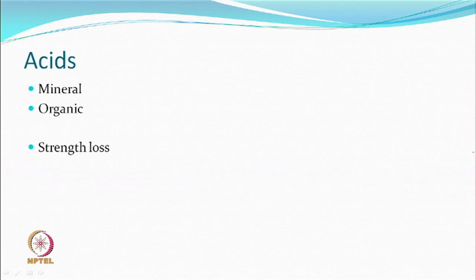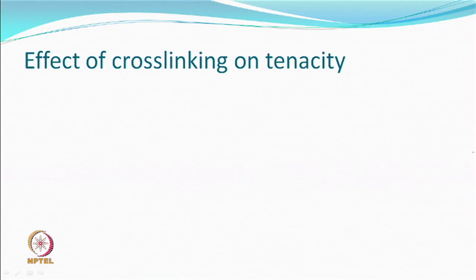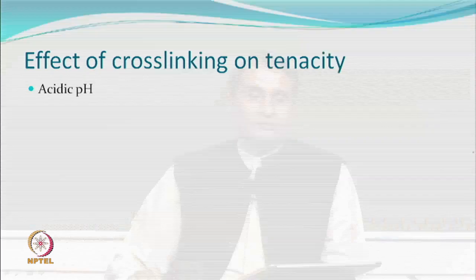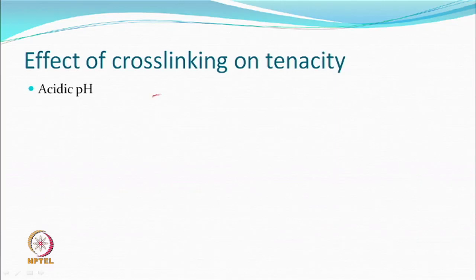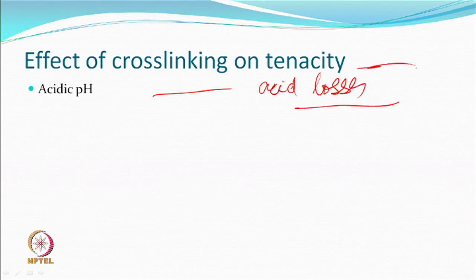And so people would like to not use the acids directly for catalysis, but use something else as catalyst, because of strength loss. I'm sure you know the cellulose can be dissolved, or at least there's a test method in sulfuric acid. So it means it can degrade. So when you go for higher temperatures also, strength loss can occur. So one may like to remember that whenever you do cross-linking in a manner in which we have just described, the tenacity is going to reduce because of the acid, so we call them acid losses. We are talking in terms of tenacity, we are not talking in terms of mass. So cellulose is sensitive to acid. All ether links are sensitive to acid.